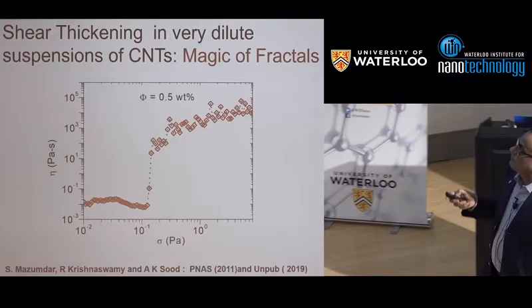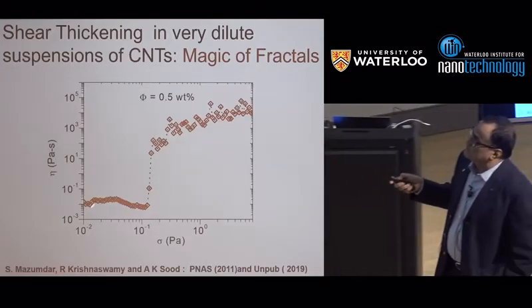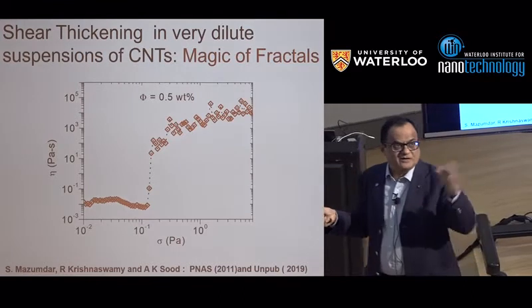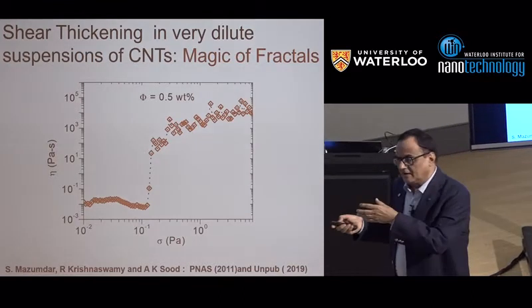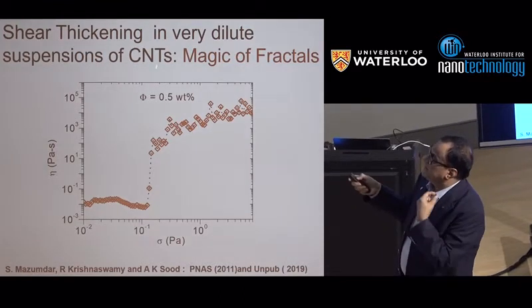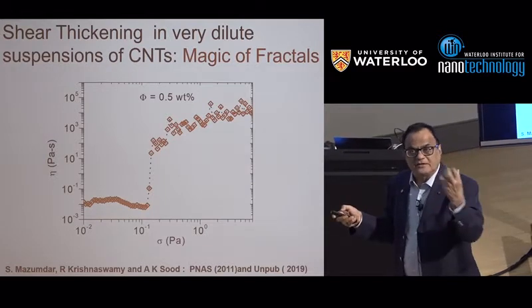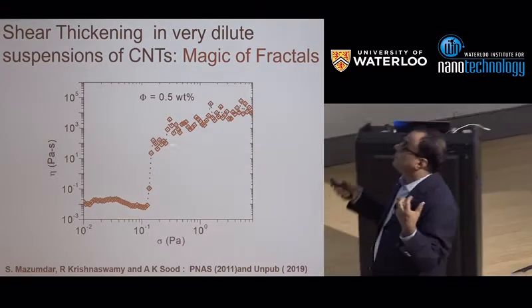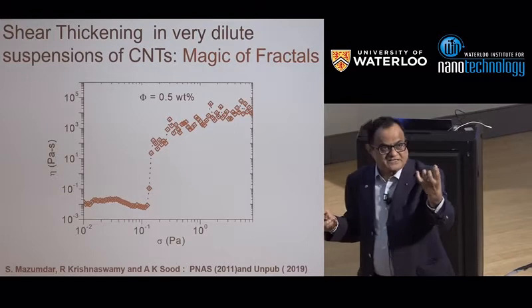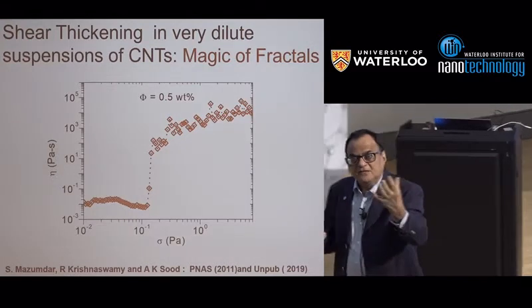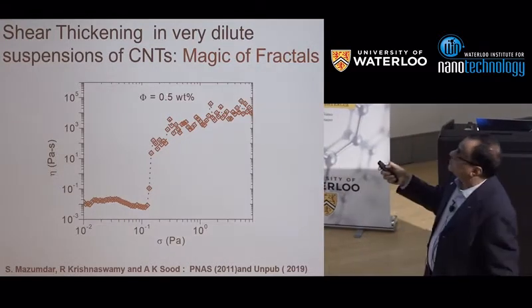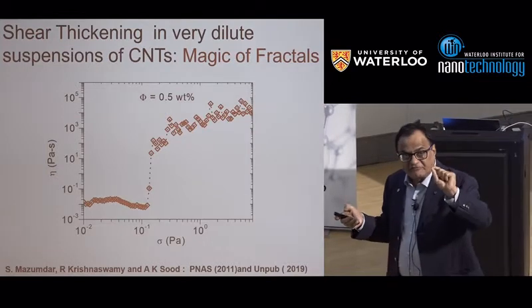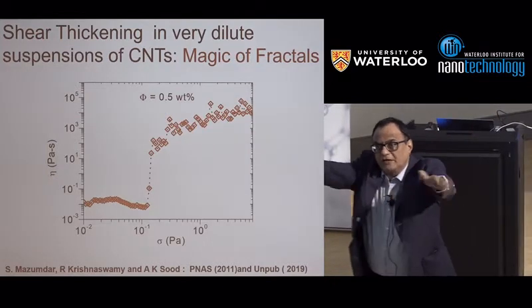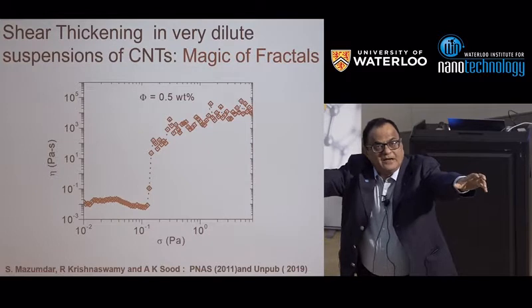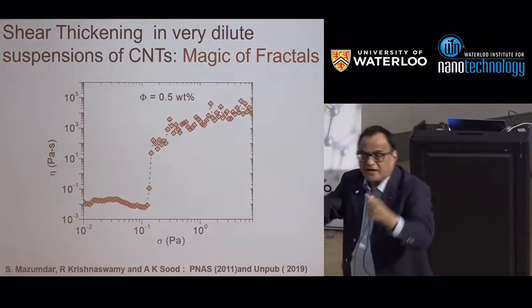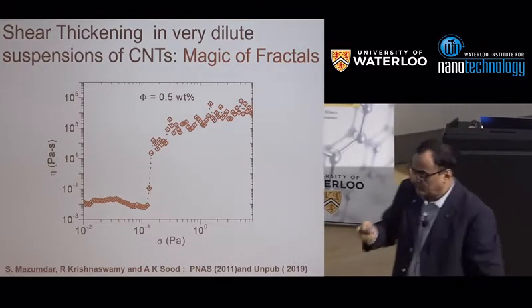So what we did was, when I was working on carbon nanotubes for devices, we had this idea that we take nanotubes in a solvent where they do not disperse. So they form fractals, or fractal objects. So they are highly fractal. Even when the weight fraction is only 0.5%, not 50%, they form this percolating fractal structure. And what we are now playing with is the fractal friction.